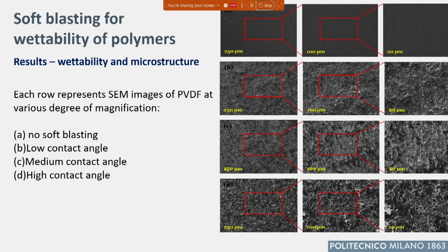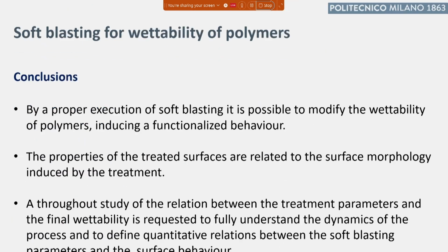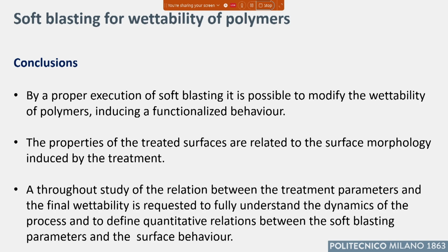Okay. How can we conclude? Indeed, this study confirms that by means of soft blasting, it's possible to obtain super hydrophobic surfaces. First of all, it's possible to modify the wettability behavior of polymers and induce a functionalized behavior. Also in this case, a more accurate study on the treatment itself must be done to completely assess the relation between the treatment parameters and the final behavior in terms of wettability.